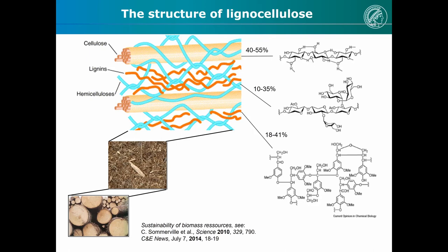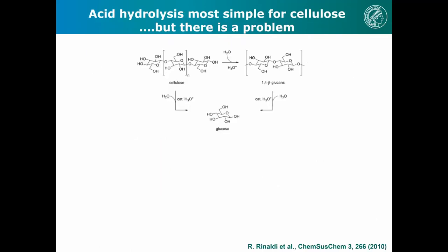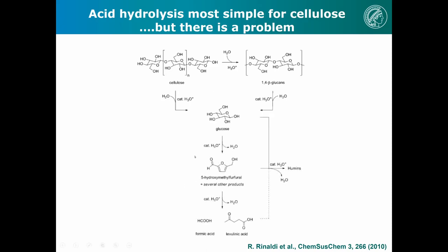In principle, chemists know what to do. The glycosidic bond is actually normally quite easily split by acid catalysis. So that's what happens. So we use acid catalysis, and even this protective glycosidic bond can split. The big problem is, as soon as you are here, polyhydroxy alcohols like sugars, they continue to react. And the same catalyst which splits the glycosidic bond catalyzes all these other reactions. And you have to work under harsh conditions, otherwise you wouldn't split the bond. So all these reactions go on, and the worst one is the formation of humins, brown, gooey, bad stuff.